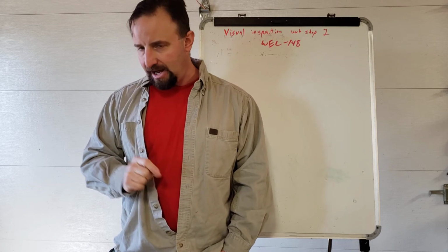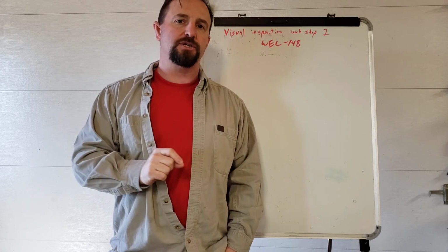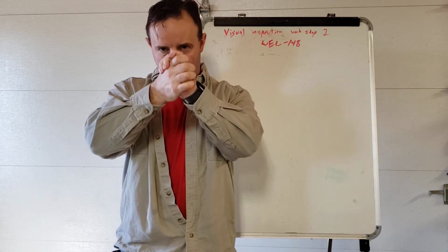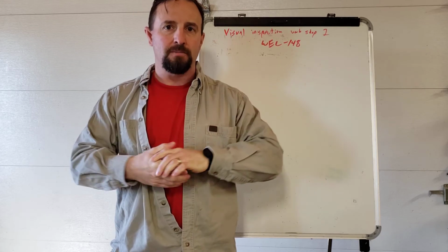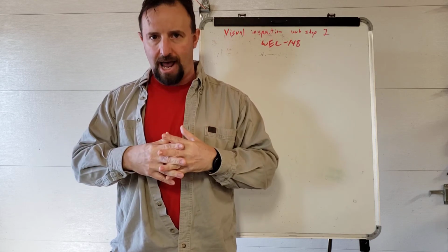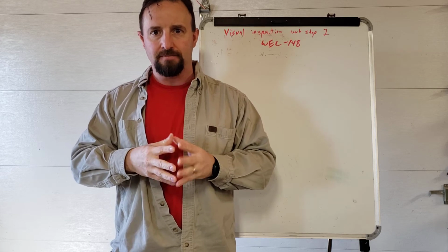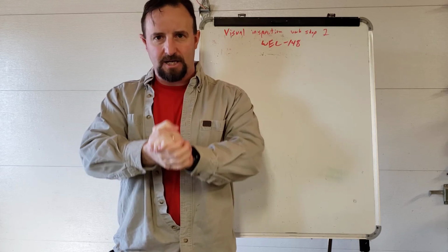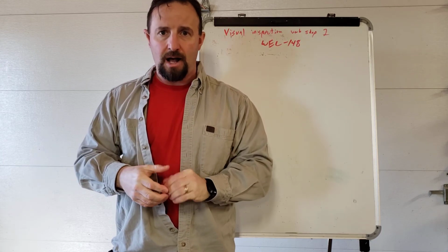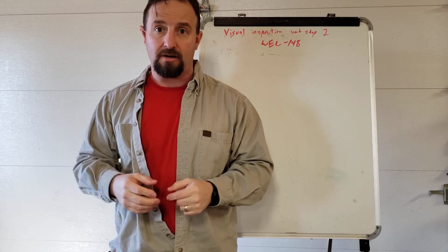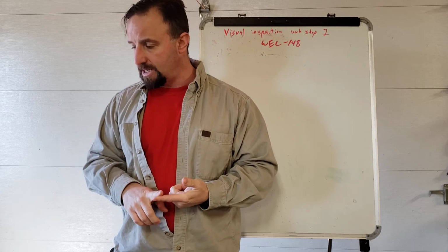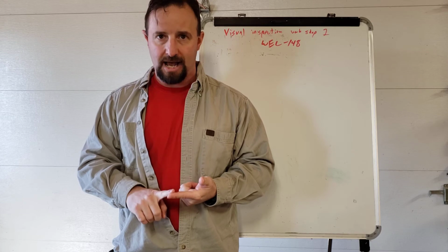And if you have a tungsten inclusion, especially if you're TIG welding in aluminum, it will crack. There is no way it can't, because that tungsten is so dense that it just sits there. Aluminum is very, very light, very, very soft in comparison, and aluminum is very, very thermally reactive. So as that weld expands and contracts around that tungsten just sitting there like a nice little diamond inside there, and it can't move, as the weld squeezes around it, it's just going to crack. And once the aluminum starts cracking, it will keep cracking. Tungsten inside a weld, especially inside an aluminum weld, is absolute death.